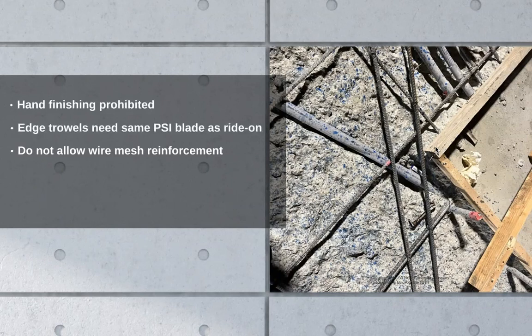If you're going to have a polished concrete floor, a lot of times subcontractors doing a standard cast-in-place are going to hand finish around all the columns and all the edges. Here's a question: is the PSI they're able to apply with a hand trowel going to leave the exact same surface as underneath an eight-foot, ten-foot ride-on or a walk-behind power trowel? The answer is no. That's why you often have almost a frame-like edge in your concrete — a little lighter, cured differently — showing all the areas where someone hand troweled.